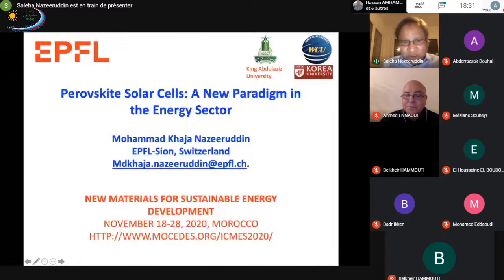However, if you look at the processing conditions for silicon solar cells, they are extremely hot, high temperature, with several steps involved and very clean room facilities. Compared with this, perovskite solar cells use a solution processed material which self-forms a three-dimensional material encapsulated between the hole transporting material and electron transport material. This gives you a 25.5% efficiency. However, there are minor issues, which are some stability issues and toxicity issues, which I will discuss as we go in the presentation. So what is perovskite material?